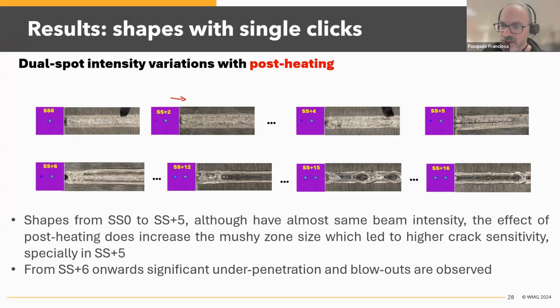There is a central crack happening, and then as we keep moving, we have problems with blowout, probably a bit of humping, and even lack of penetration on the bottom plate. You can see it is very extreme. There is a massive blowout, lack of fusion, and lack of penetration on the bottom one. So this is the extreme case with the 2 dots, front and rear.